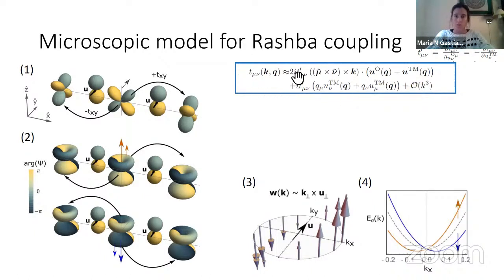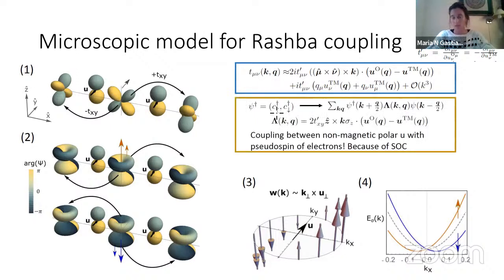And now, once you do the transformation from the T2G orbitals to the spin-orbit coupled bands, as you spin up and down, then you get this kind of 2x2 matrix where the pseudospin up will see exactly the opposite of the pseudospin down band. And again, because I had this T to the right and to the left as a sign, this coupling will be proportional to K, and so it also breaks inversion. And that's basically how you can get that non-magnetic polar displacement coupling to the pseudospin of the electrons.